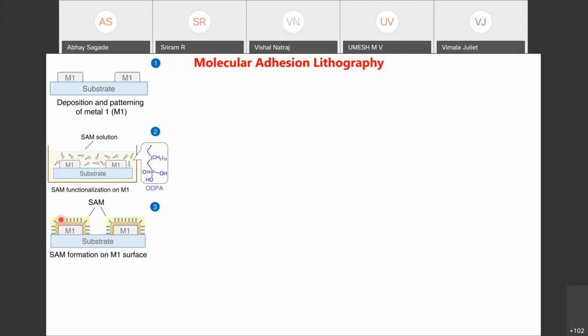Please note here that not just the top surface, but the vertical edges of the metal are also occupied by the 90-degree orientation of these SAM molecules. What you can notice is that the empty region between the two metals, which is a standard silicon dioxide substrate, has no SAM molecules present. That's why in the next step, you can deposit a second metal, which does not get attached to or interact with this molecule, globally everywhere on the substrate.